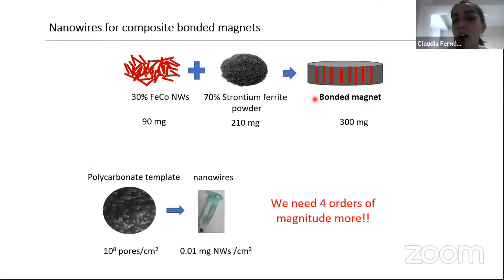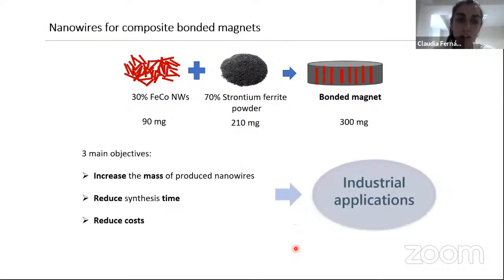So if we think about the production of a bonded magnet of 300 milligrams, we will need to produce 90 milligrams of nanowires. And in a common laboratory process, using a polycarbonate template, we were able to obtain 0.01 milligrams of nanowires. So we need 4 orders of magnitude more to provide the amount of nanowires to produce a bonded magnet. So this work has 3 main objectives: to increase the mass of the produced nanowires, to reduce the synthesis time, and also to reduce the cost of the process.